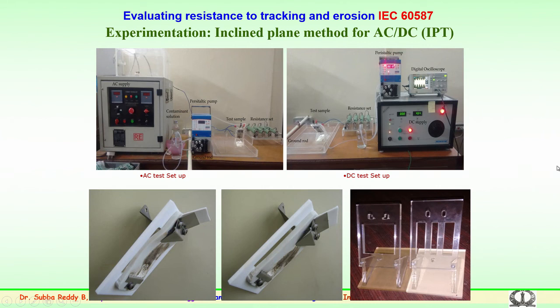For DC, the standard has not been evolved. For AC experimentation, standards have been evolved. These are the arrangements of the electrode. These are the electrodes. This is the sample holder and the sample, which has been fixed at a known distance. In this arrangement, the perspex sheet at a 45 degree angle is where the sample is mounted with the electrode arrangement shown here. This is how the fabrication has been done to make the sample and the arrangement as per the 60587 standard.